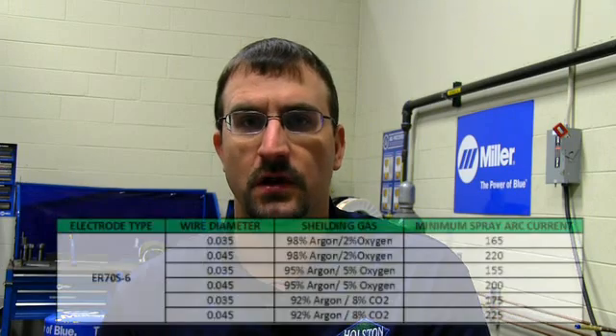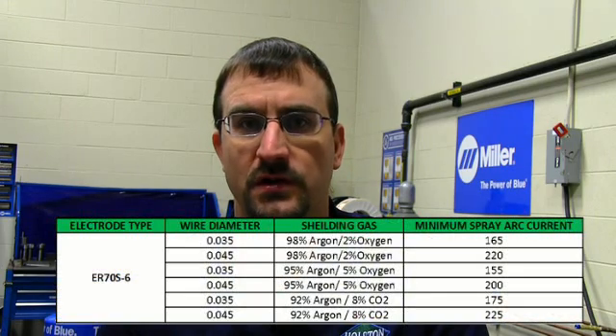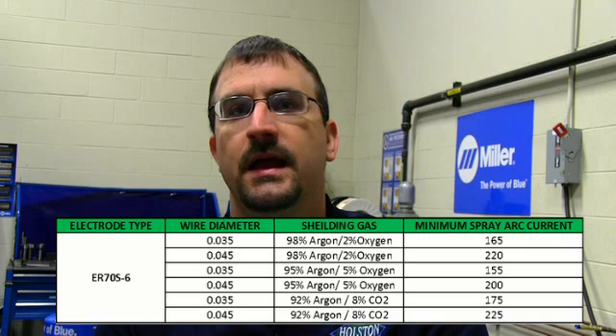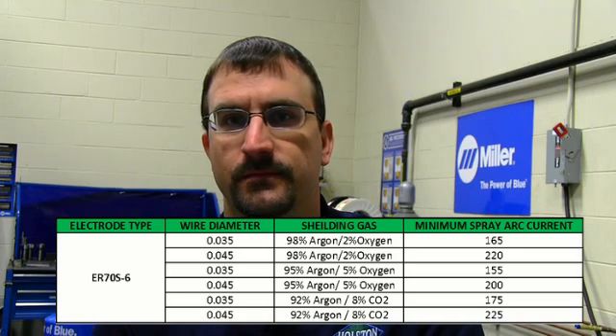To achieve spray transfer, it is necessary to have a minimum of 80% argon in your gas blend. Also, it is necessary to be above the globular to spray transition current. Now, the next question you should be asking yourselves is, what is a globular to spray transition current and how do I know what that is? Well, that's a good question, and the globular to spray transition current is going to change for every given wire diameter and gas mixture. So as you can see, here's a chart that shows the different globular to spray transition currents for different wire diameter and shielding gas combinations.